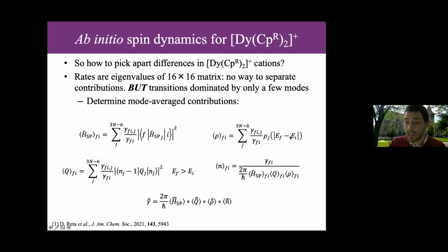Then we have the density of states part, which relates to the line width function and how close in energy you are. We have the statistical occupation part, and we take each of these elements and we weight them by how much the jth vibrational mode is contributing to the total sum over all vibrational modes. And so we're essentially averaging these parts of that rate expression. And by doing that for the spin phonon density of states and occupational term, we can then compare this product for any single matrix element to the total rate to then obtain an effective number of modes.